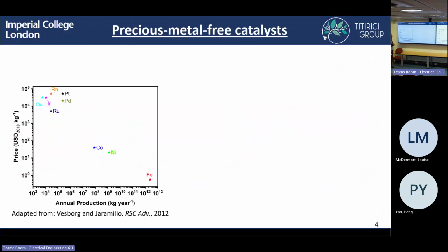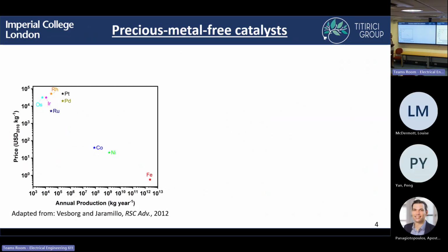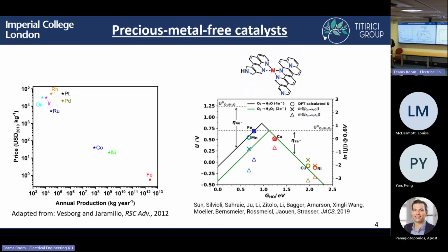And obviously it makes sense to try and move away from these precious metal catalysts, which have a low annual production and a very high cost per kilogram, moving towards precious metal-free catalysts such as cobalt, nickel, or ideally iron, which is the lowest cost and the highest annual production. If you then try and make single atom catalysts, we see that the most active of these is iron. So this is quite promising since it could potentially lead to a really low cost and similar activity to platinum.